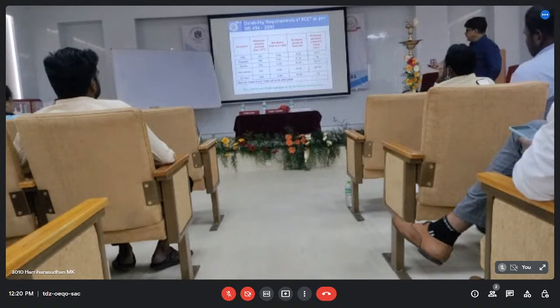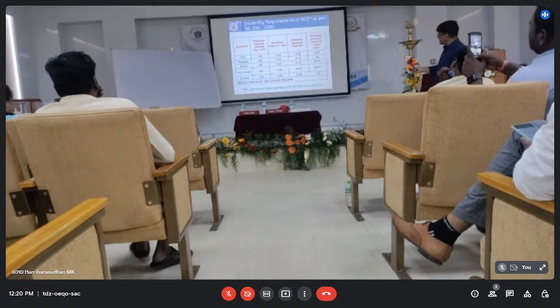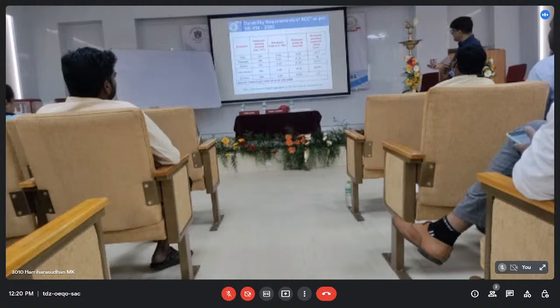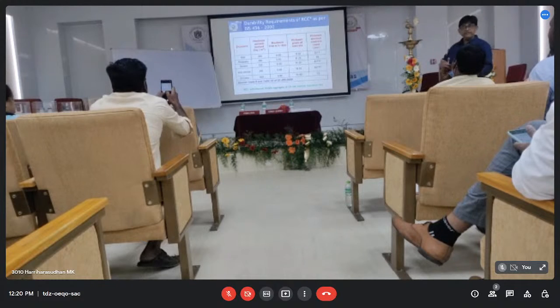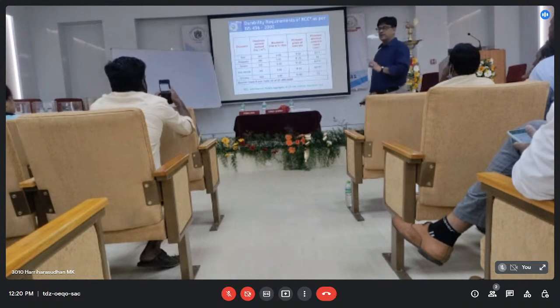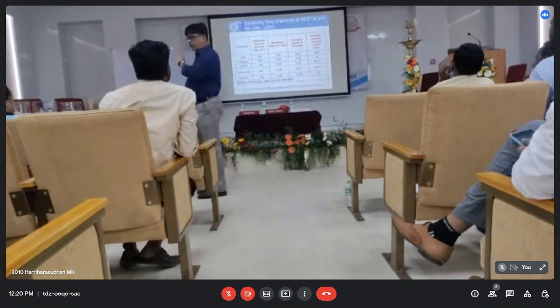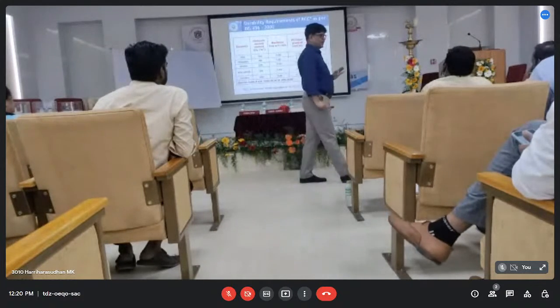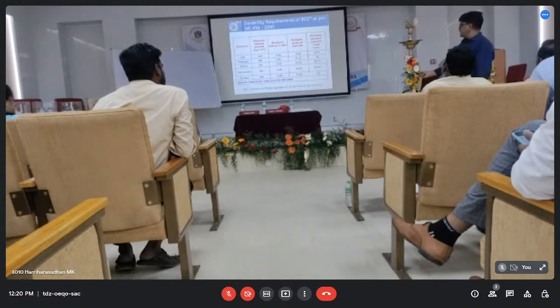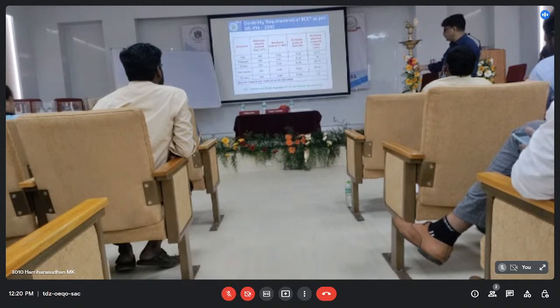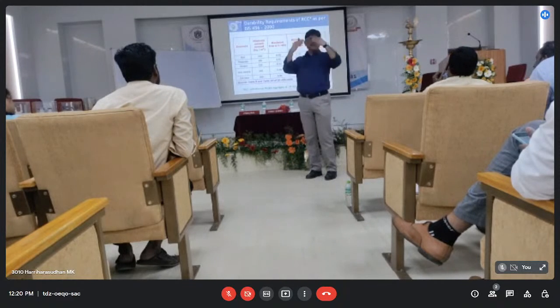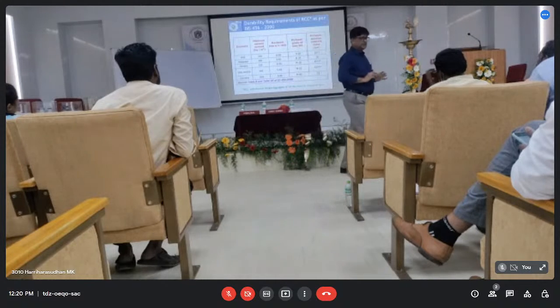Table 5 and table 16. If your exposure situation is this, your minimum cement content, maximum water-cement ratio, minimum grade of concrete, and minimum nominal cover are defined in the code. Suppose I am in Chennai. Chennai normally goes between severe and very severe. Your minimum nominal cover should be 45 mm. Minimum. 25 mm exists nowhere in the code. Whether it is a column or a beam, everything should be 45 mm. If you are going to substructures, it will increase, because that will be extreme. You have to go beyond, 50, 60, 70. Substructure environment condition is separate, superstructure environment condition is separate.